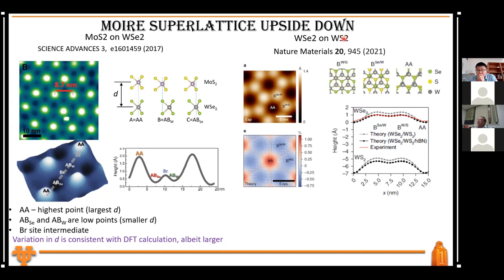So it's very similar to what we have, except here it is WS2. But in terms of lattice mismatch, it's about the same, right? The only difference is here you have WSe2 on top, and here you have WS2 on bottom. You look at that STM image, you may say, well, what's wrong? You see the moiré pattern, you see the moiré periodicity. But it turns out the contrast is reversed, exactly the reverse of what we observe. Both are experimental data, both cannot be lying. But why, just by flipping one upside down, do you see such a large contrast?